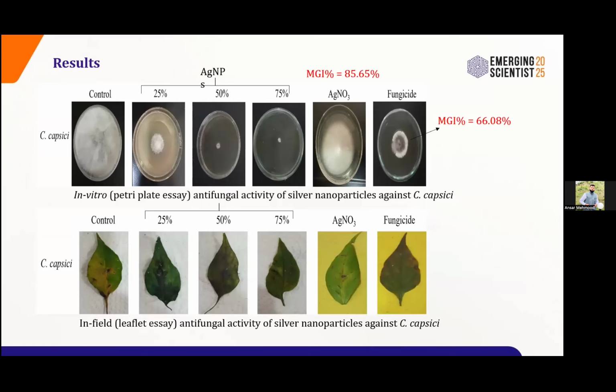Here is the application of nanoparticles. We used them against anthracnose disease, which is caused by Colletotrichum capsici, a fungus which causes anthracnose in chili plants. So we isolated that Colletotrichum capsici from the chili plants, and then the in vitro analysis showed, here we use a control, and 25%, 50%, and 75% silver nanoparticles, and silver nitrate solution as a control, and then the fungicide mancozeb was used as a positive control. So we clearly see that at 75% of silver nanoparticles there is only a little growth of Colletotrichum capsici, while in the control the plate is full of Colletotrichum capsici.